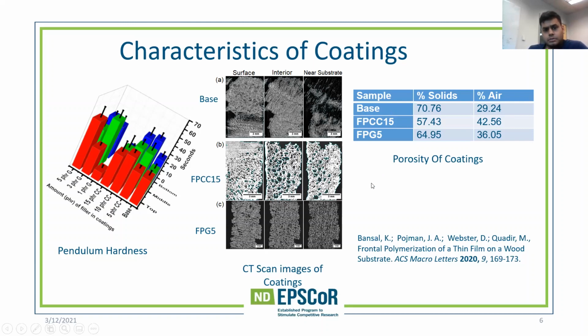Then we had another technique with which we studied the surface profile of the coatings. And here are the CT scan images of the coatings. Top row shows the base, surface, interior, and near substrate, meaning the part which is near to the substrate. Interior is somewhat 50% depth, and surface is on top. As we can see, there are pores in the middle of the coating, and the coatings are uniform, and the pores of the graphene coatings are very different from the pores of the calcium carbonate ones because they are two different types of fillers.